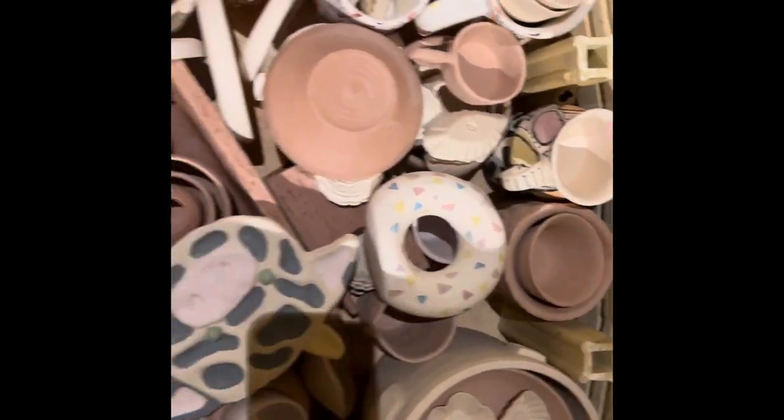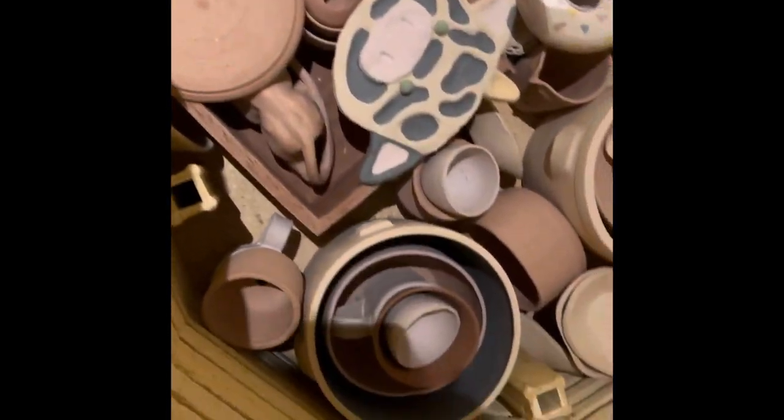In our studio, we hold them for six hours. We fire at cone 011, sometimes cone 04. That's basically what we do in the studio. This is a packed kiln and no explosion. Just don't load anything that's cold to touch — longer drying time, less than half-inch, and be patient.